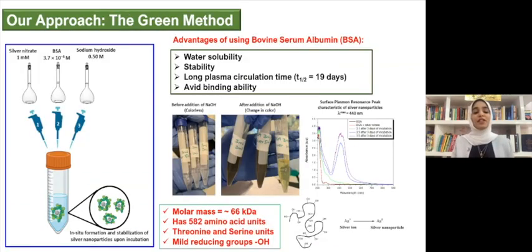So BSA actually has a molar mass of around 66 kilodaltons, and that's important. I'll come back to it later. It has 582 amino acid units, of which the majority are serine and threonine units, and it has mild reducing groups on its surface. So the molar mass is a very important factor because as we have a greater molar mass, we have a higher number of the hydroxyl reducing groups. And the role of this hydroxyl reducing group is to reduce the silver ion to silver nanoparticles.